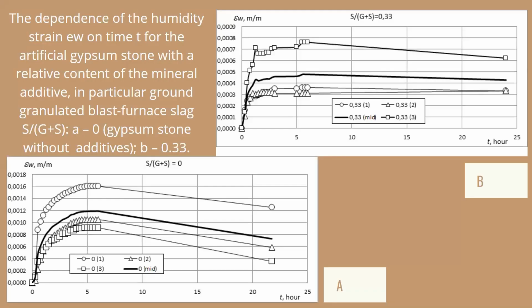Figures and table show us that as soon as the specimens are immersed into the water, their length starts to elongate immediately due to humidity strain, the swelling. The strain developed during 3 to 5 hours, and after that it attained a maximum value, and almost immediately it began to come down.